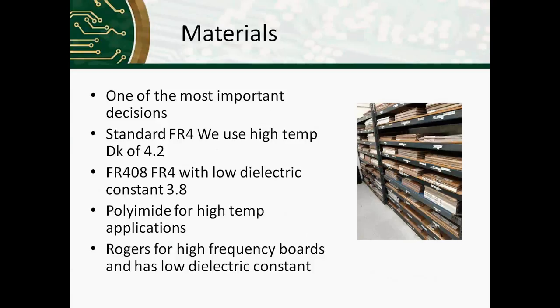FR408 is another flavor of FR4. It has a low dielectric constant of 3.8. We also regularly use polyimide for high temperature applications, as well as Rogers material for high frequency boards that also has a low dielectric constant. Data sheets for all these can be provided for any of the material you might be interested in, either by us or by going directly to the manufacturer's website.